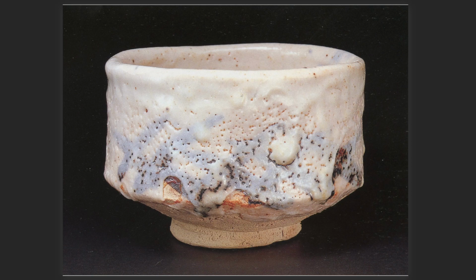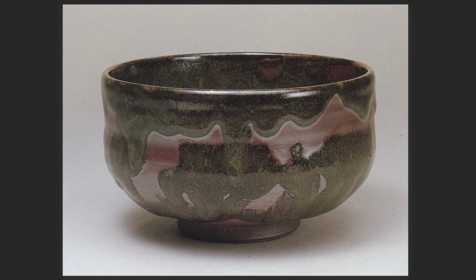This kind of glaze doesn't have a really smooth feeling to it. It's more like an eggshell. It's more like it needs a couple more cones to get shiny. And that would be overfiring in the mind of the maker. So there's iron painted under it. Glaze is gathering up in little globules. Very distinct tactile presence.